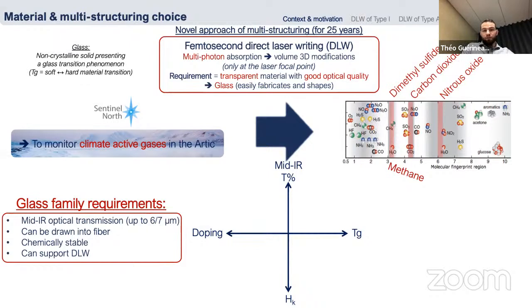Of our glasses, there are mid-infrared transmission, the concentration of doping elements, whether transition metal or rare earth, the hardness, the HK, and the glass transition temperature, TG. One of the most common glasses manufactured in the world is the silicate one, with a very high TG and hardness, but the mid-infrared transmission and doping concentration are not so good. In the opposite, we have the fluoride or the telluride with good solubility of doping elements and a good mid-infrared transmission. Then we have the chalcogenide that can be doped a lot with doping elements, and are well known to not have very good mechanical and temperature properties, but they still have a mid-infrared transmission that could be above 25 micron.